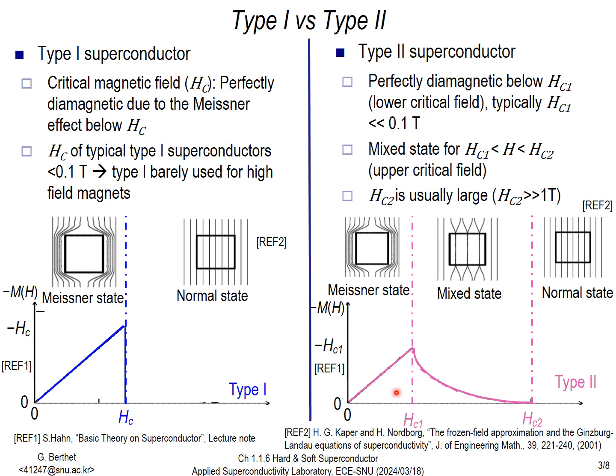On the other hand, Type 2 superconductors initially follow the same behavior until their first critical field, denoted Hc1, and then reach the mixed state. In the mixed state, the magnetization curve is nonlinear and decreases as the field increases until reaching zero, where the superconductor is driven to its normal state. While Hc1 is usually lower than the critical field of the Type 1 superconductors, Hc2 tends to be much larger, so Type 2 superconductors are usually good candidates to make magnets.